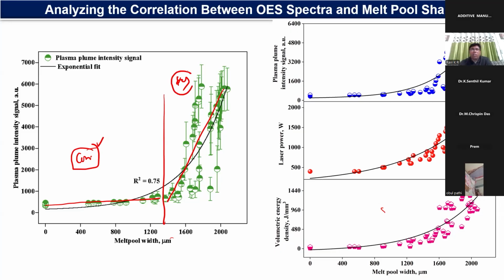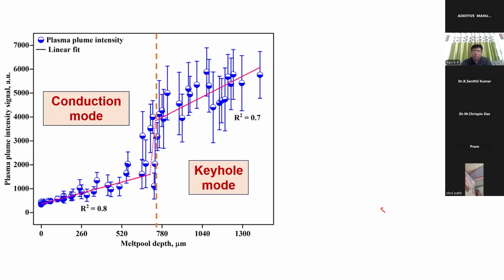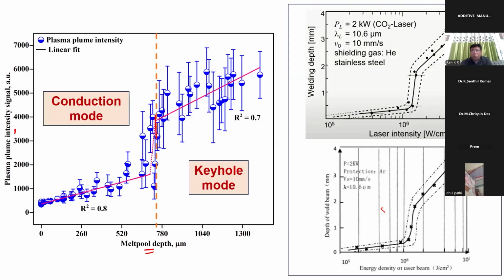Once you jump into this keyhole regime, there will be a lot of defects. In a similar way, we have tried to correlate the melt pool depth with the plasma plume intensity. Again, in this case also, you get a non-linear correlation. Then we were able to get the conduction to keyhole region transition.